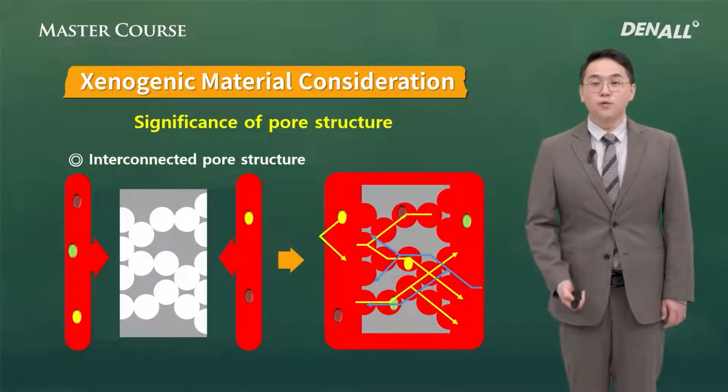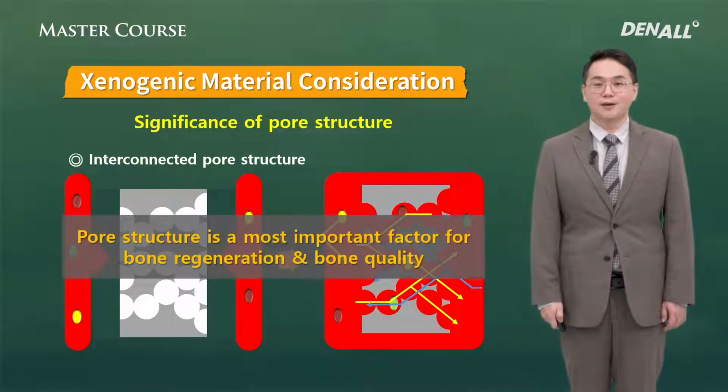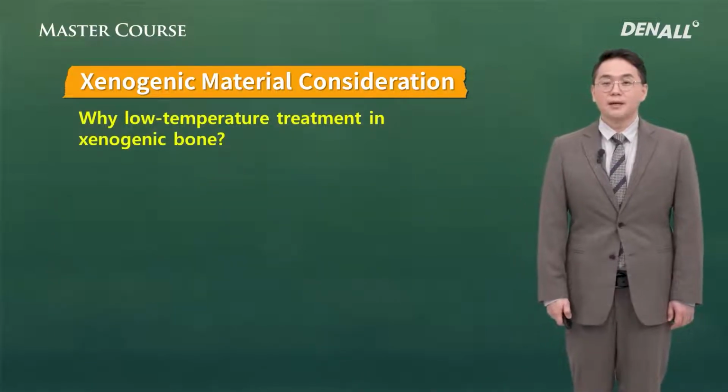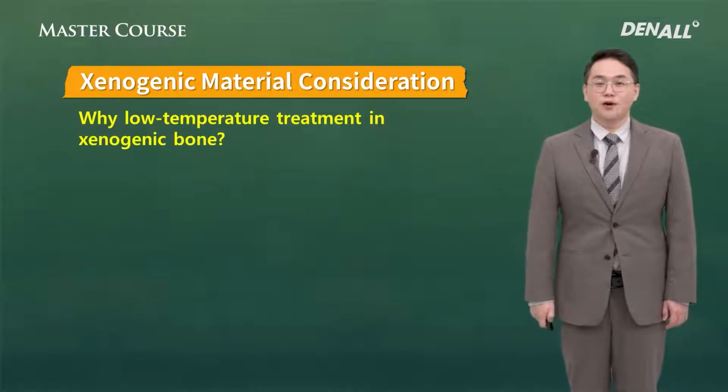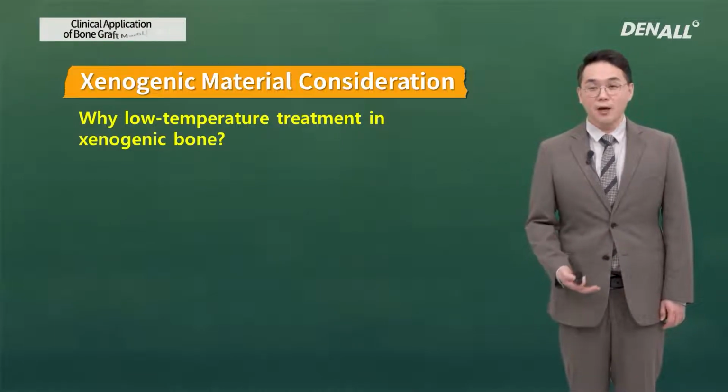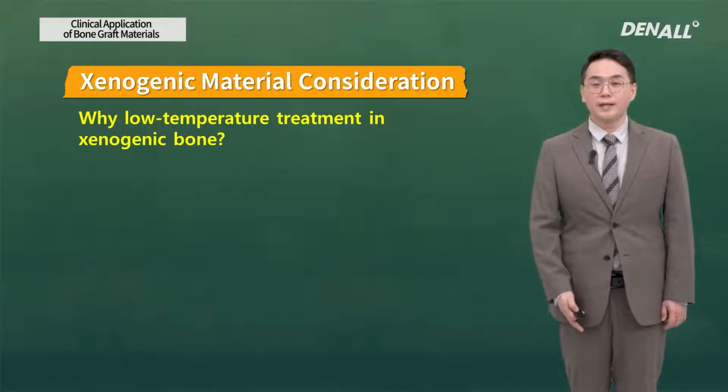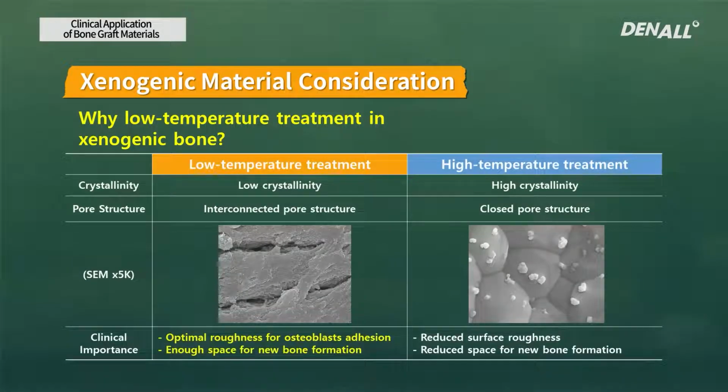So a good bone material should have a porosity structure that is similar to human cancellous bone. I talked about removal of organic material through heat treatment that's burnt out. Depending on the temperature, the basic structure would get varied. The purpose of using the low temperature treatment is to remove the organic material while maintaining the bovine or porcine cancellous bone similar to human.